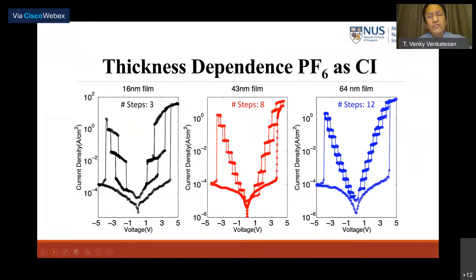But now, why is it 3 units of switching? It is 3 units of switching because this PF6, which is a counter ion that's sitting next to the molecule, is a relatively big molecule. So when the ion switches from one hysteresis curve to the other, the PF6 molecule changes position in space and forces the layers above and below to switch. So you end up having 3 units of switching rather than 1 unit of switching.